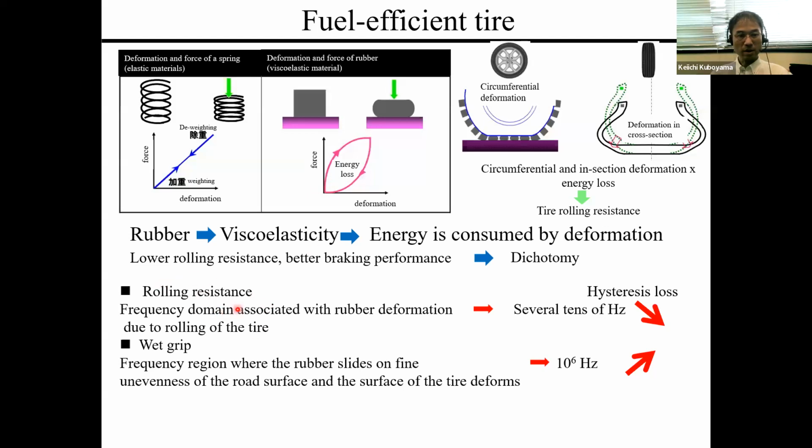So it is good. And when you think about wet grip braking performance, this phenomenon is related to high frequency properties, around 10 to the 6th power hertz. So when you improve the wet grip property at this frequency, you can get a good braking performance.